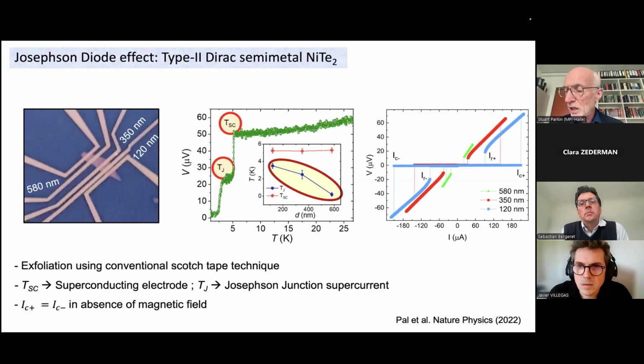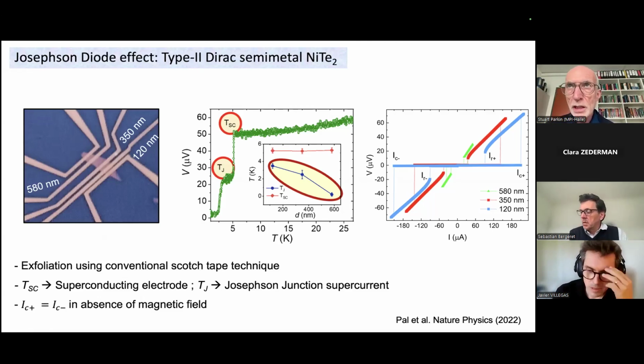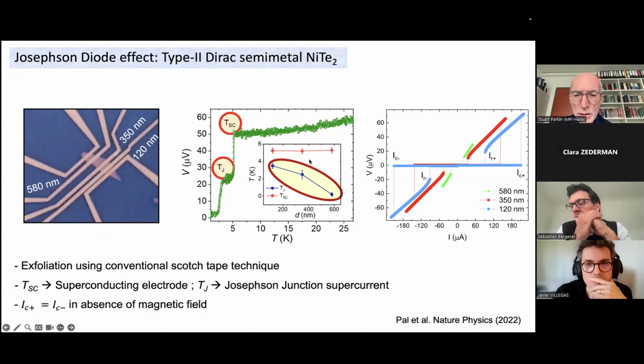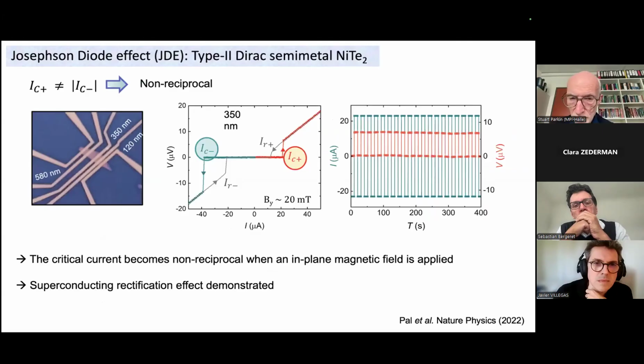So in fact, in some other materials, which I won't have time to discuss, in platinum ditelluride, we've demonstrated that we can flow supercurrent through that material over more than 1 micron. So it's quite extraordinary that we could stabilize supercurrent flowing through these Dirac semimetals over very, very long distances, which is amazing. And you can also see in the middle that the temperature at which we see the supercurrent flowing through, in this case, nickel ditelluride, will decrease as we increase the separation between those niobium electrodes.